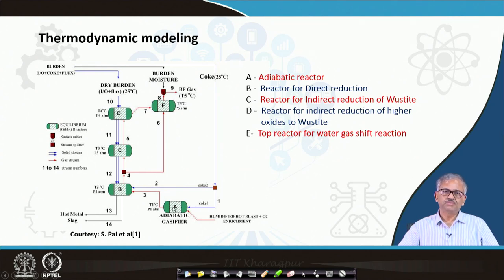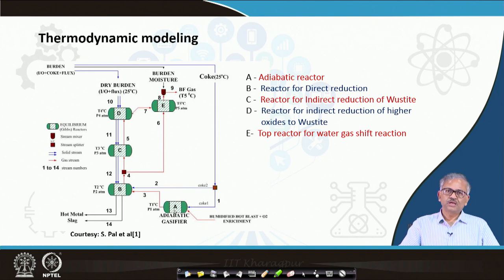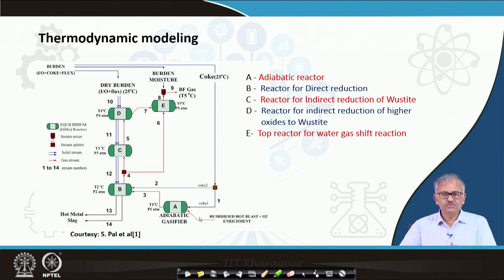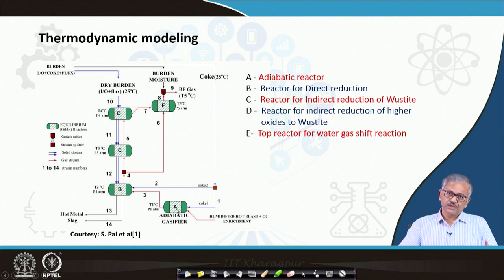You can calculate the heat generation from the heat of reaction. Using FactSage — which is a very good thermodynamic database — you can calculate what will be the total heat effects and what will be the final composition of the gas. You are giving coke, humidified blast, and some oxygen enrichment. Some oxygen enrichment of the air blast is done — usually 21 volume percent oxygen, but you can make it 23 or 25 percent — and you can also give some moisture into the air blast. So, FactSage can calculate the total heat effects, the temperature of the gas, and the final composition.